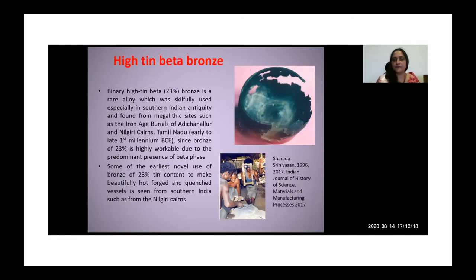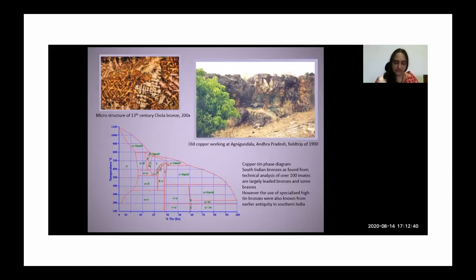And as Padma was mentioning, these are among some of the earliest such known hot forged and quenched vessels. And as you can see, that vessel from Adichanallur has a very, very thin rim, and it's been forged into this kind of shape, which is quite extraordinary skill, really, which even in contemporary times would be very difficult to do. And I should also mention that bronze as such is not very ductile. Brass is a much more ductile material, and brass can be sheet hammered quite easily. But bronze, and that too, leaded bronze, is not a very ductile material. It's good for casting and so on.